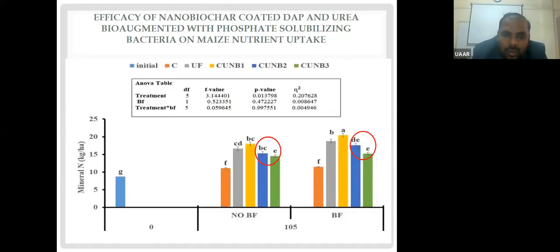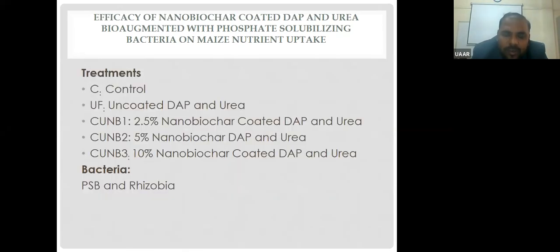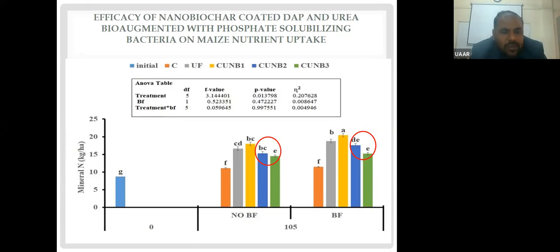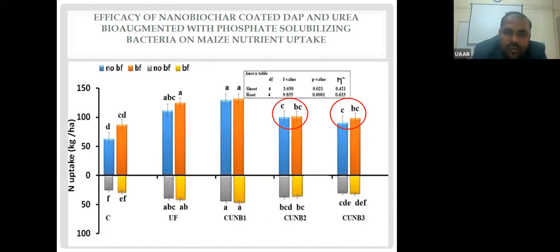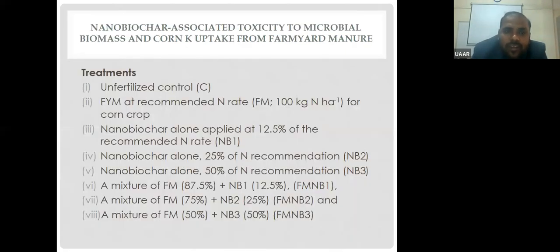And what happened when you coat at high doses like 5 to 10% on DAP and urea, then the mineral nitrogen is reduced. The same happens because you added these microbes, phosphate solubilizing bacteria and rhizobia, and these nano-biochar impact these phosphate solubilizing bacteria, reduce their efficiency, and at the end, mineral nitrogen is being reduced. And as a result, nitrogen uptake is also low at high doses of nano-biochar when mixed with these phosphate solubilizing bacteria and rhizobia.